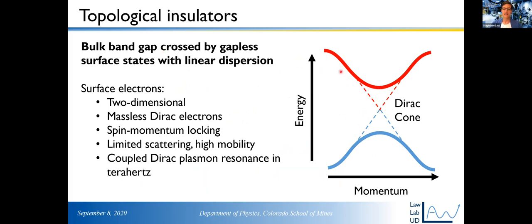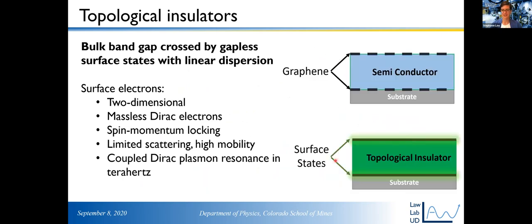So basically, a topological insulator has a bulk band gap crossed by these surface states with linear dispersion that form a Dirac cone. This might remind you of graphene, and in fact, this is the analogy that one of my former students used to use. Lots of people can understand this. Graphene, semiconductor graphene. Everybody understands this. A topological insulator is basically the same thing. If it's a thin film, you have surface states on the bottom and the top of the film. And in principle, you should have something that's bulk insulating in between.